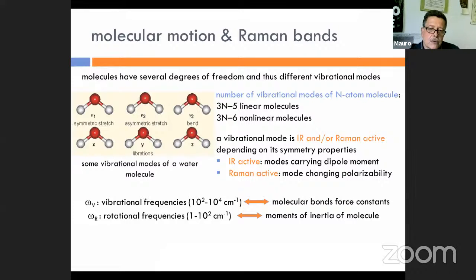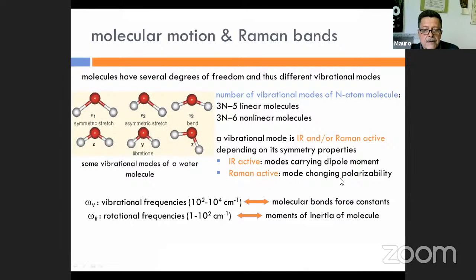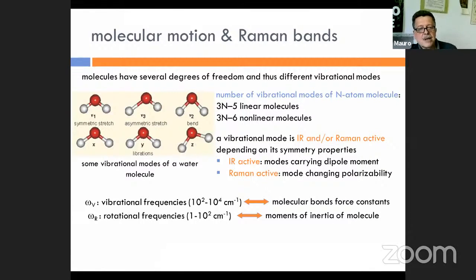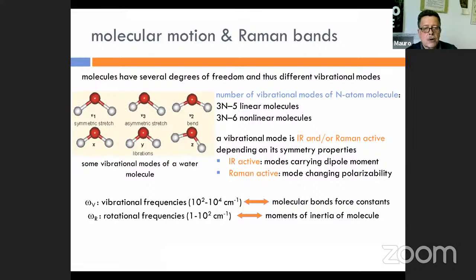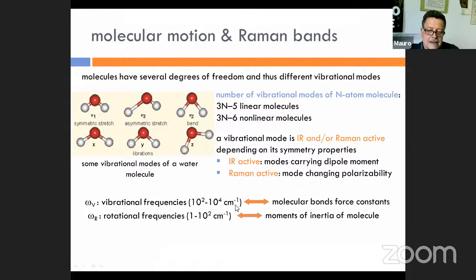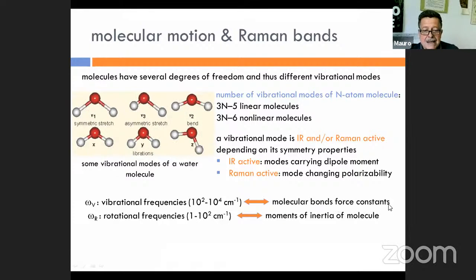A generic n-atom molecule will have several degrees of freedom, and thus will have several vibrational modes. Each vibrational mode can be Raman active if this mode changes the polarizability. As we have seen before, the polarizability must be coupled to nuclear motion. So reversing the reasoning, we see that if nuclear motion is influencing the polarizability, then we have Raman effect. The frequencies of the vibrational modes are in the 100 to 10,000 centimeters to the -1 range, and they're related to molecular bonds, force constants, and masses.